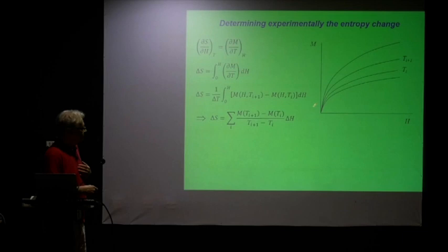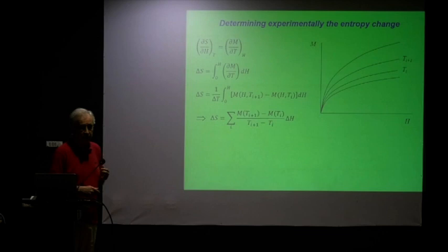We have data that look like this, let's say. This is the field dependence of the magnetization at various temperatures. So let's say if we're at high temperature, it may look like this. At low temperature, it may look like this. And this is the temperature interval. So when we look at it like that, then the entropy change is just the difference between consecutive magnetization curves,